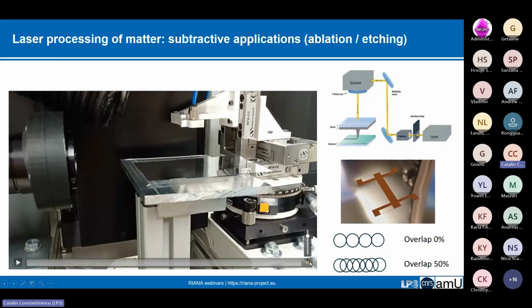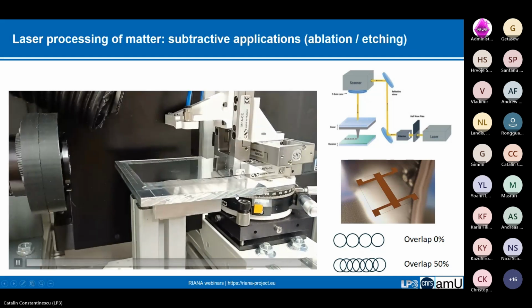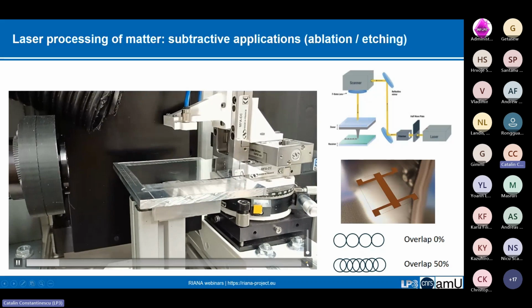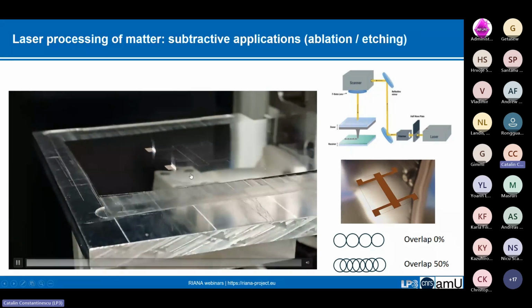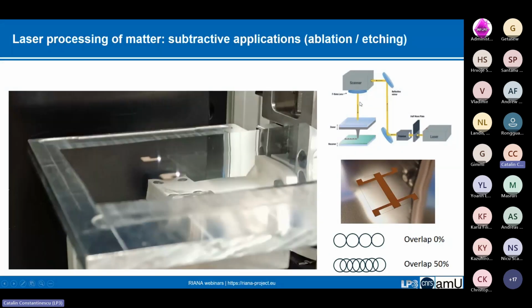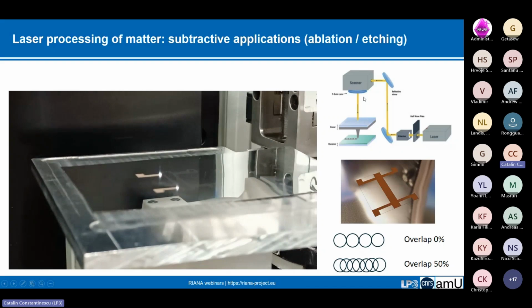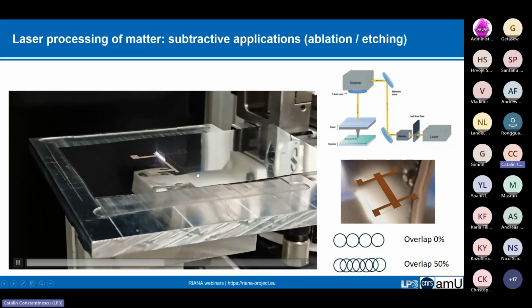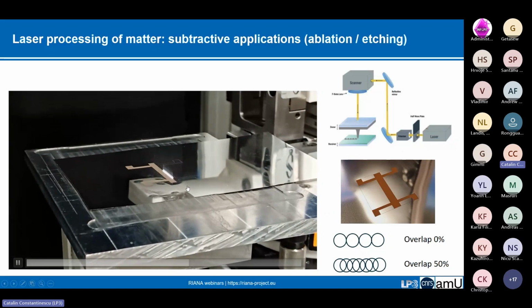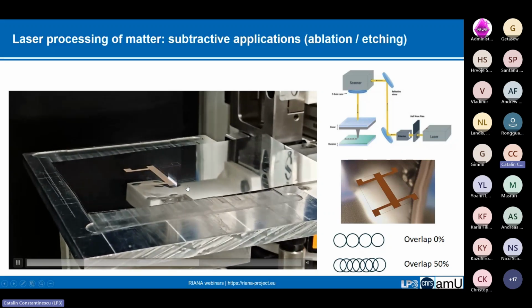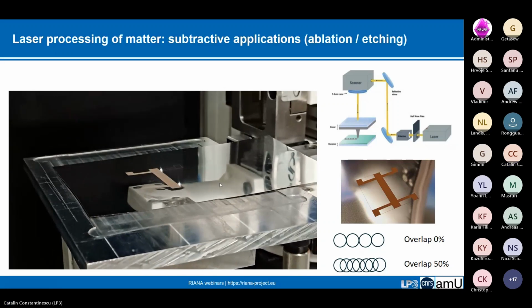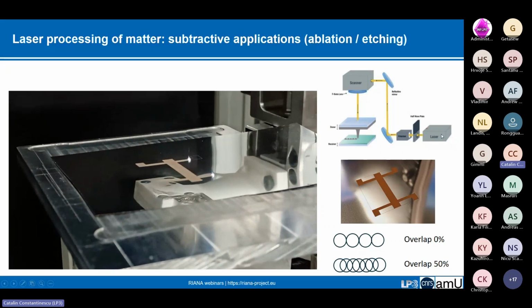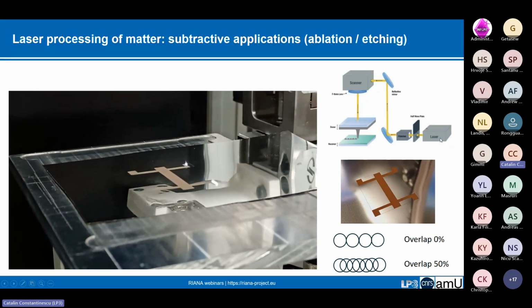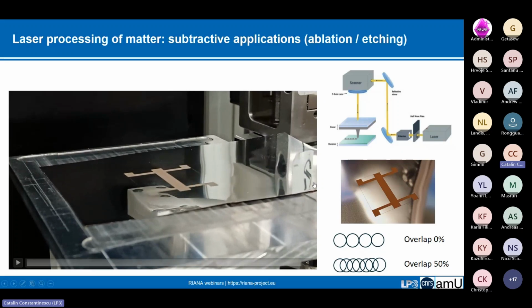and for that I will actually show you the video. It will speak more and better than I do. So here it goes. Actually, I think I can leave the sound. So the scanner provides direction. It's the laser beam at the surface, and by scanning the surface, we remove the material. In this case, it's Kapton, which is polyimide, a flexible polymer highly used in electronics. The laser is an ytterbium YAG tunable laser, picosecond, femtosecond, so we can control the thermal effects on this substrate.